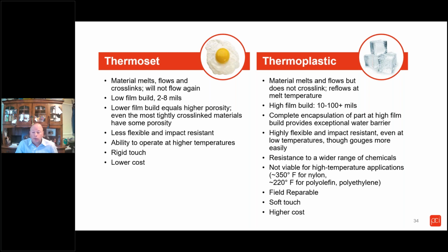They tend to be high film build coatings, which is part of the reason they provide such great corrosion resistance, anywhere up to 100 plus mils. You're completely encapsulating the part, creating an exceptional water barrier.